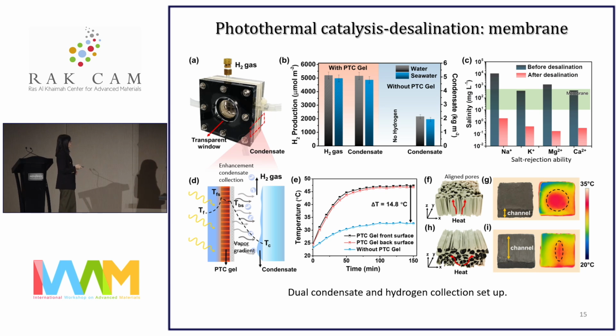And then a dual condensate hydrogen cell has been set up, as shown here, and hydrogen can be produced from both water and seawater, and the condensate can be collected as well. Here you see that the salt rejection ability of various ions can reach up to 99.9% for this system. The enhanced condensate collection is associated with the confined photothermal heating at the feed membrane interface. This can be reflected in the temperature difference between the two, with and without the photothermal membrane, of about 15 degrees Celsius. This temperature difference then creates a favorable vapor pressure gradient that improves the performance.